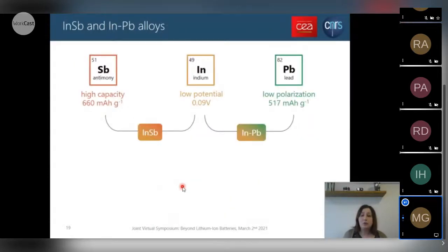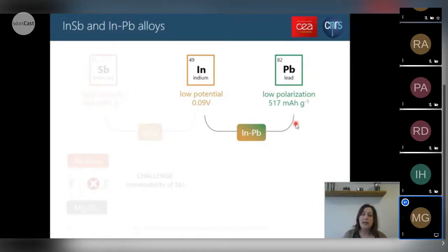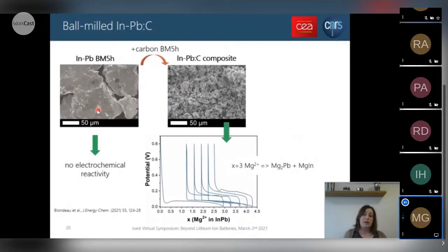So let's now move quickly to the second alloy, which is the InPb solid solution. This is also another example of phase transformation in magnesium alloys. In a similar way to InSb, we produced an InPb solid solution through five-hour ball milling of indium and lead powder. And this is what we obtain. We really obtain coarse particles on the order of 200 micrometers. And consequently, we couldn't get any electrochemical reactivity from these particles.